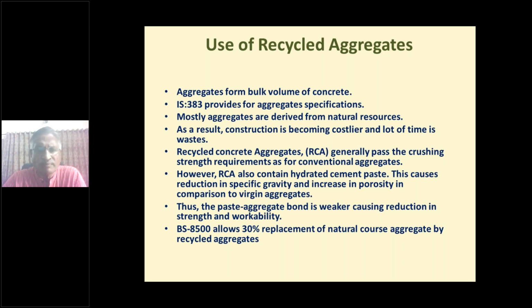But one of the major problems is the paste in the aggregate. However much we clean the aggregate, some paste remains. So that is why we are not allowing full percentage. We are allowing a much smaller percentage. The British standards are allowing 30% or more. But the Japanese are using a whole lot higher percentage of aggregate, because their processing procedures